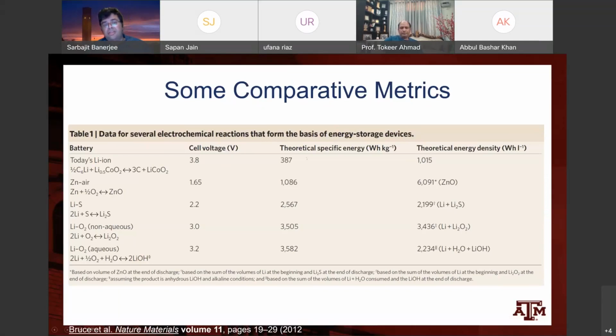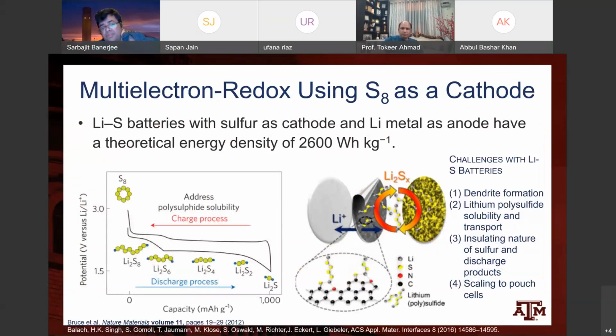So current lithium ion, this is the capacity, as you can see, 387 watt-hour per kilogram, and the theoretical energy density is here. Lithium sulfur can be much higher, about 2200. Lithium air in a non-aqueous system can be 3500. So really high capacities can be unlocked if you end up using this. So lithium sulfur is more advanced than lithium air, but still not yet at prime time. So the point is that you can take sulfur S8 and reduce it by forming these lithium polysulfides, and you go through a sequence of reactions. So Li2S8, Li2S6, Li2S4, and then Li2S2 and lithium sulfide.